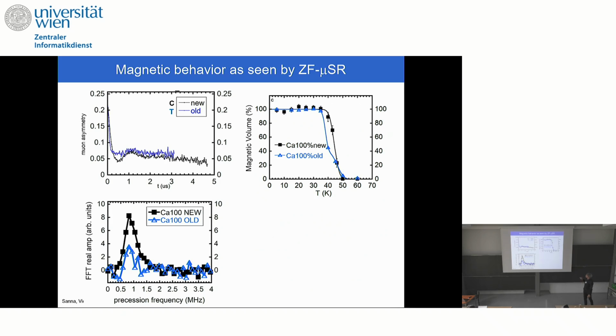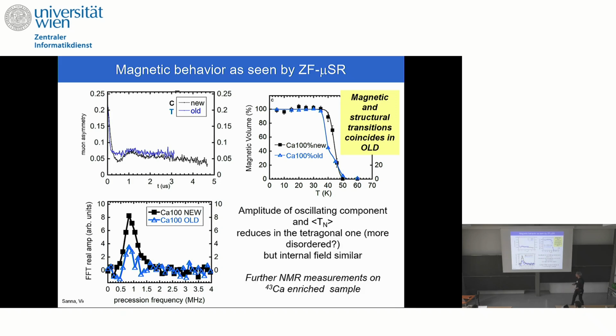And just to conclude, the magnetic volume plotted as a function of temperature for the two samples shows that, okay, maybe the magnetic temperature is changing slightly, but essentially we don't see a very huge difference in the magnetic response of the sample. This is, in my opinion, an experimental evidence of the fact that whatever the structure, tetragonal or cubic, the main features don't change that much.